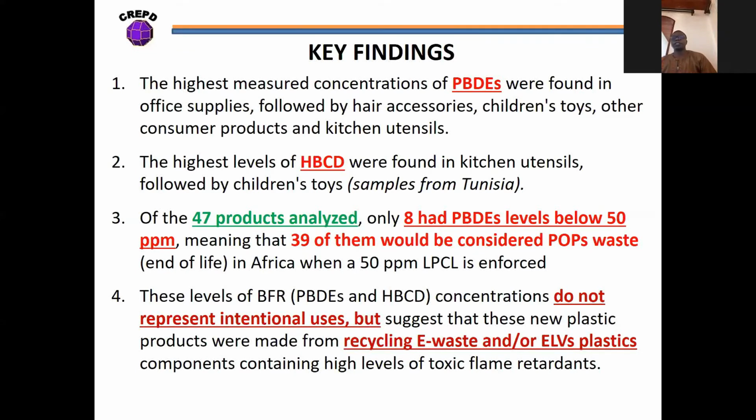Lastly, we consider that this level of brominated flame retardants, particularly the PBDE and HBCD concentrations, do not represent intentional use of these chemicals in these products, but suggest that these new plastics imported to Africa were made from recycling of e-waste and/or end-of-life vehicle plastic components containing high levels of toxic flame retardants, and this is very worrying and concerning.